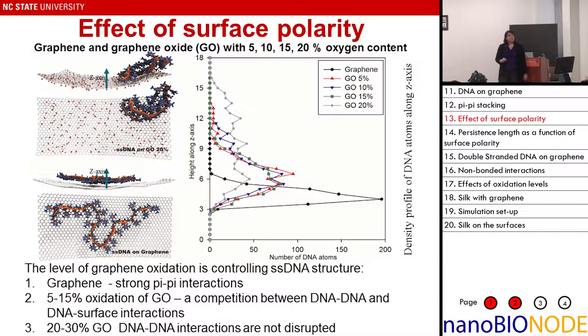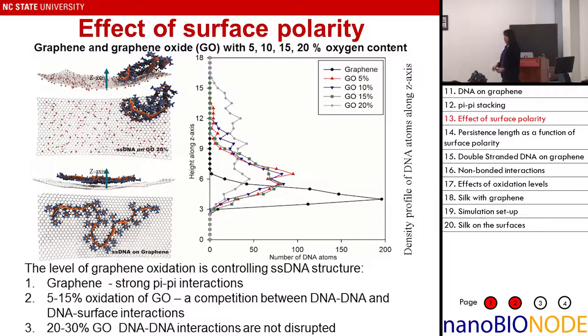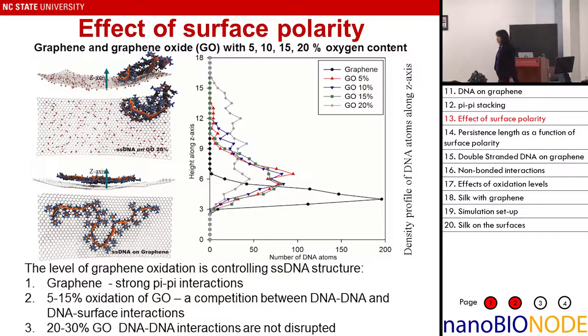Changing from 15% to 20% led to another shift, where DNA now participates only through hydrogen bonds with the surface and retains its pi-pi interactions. So we have three different scenarios. [Question from audience about bowing in graphene oxide and how height above the axis is measured.] We take the center of mass of DNA and calculate with a vector 90 degrees to the surface. The bowing occurs because putting 20% epoxy and hydroxyl groups kills the aromaticity; it's actually a free-floating small flake, and we wanted it to flex a little bit — so it was on purpose.